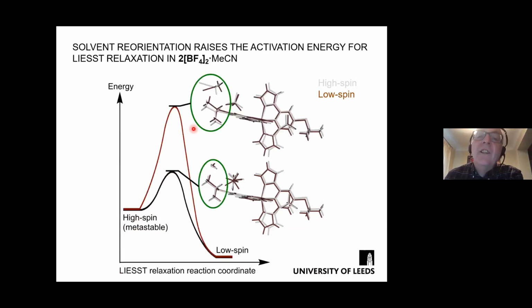And for the acetonitrile crystal, which is the one which has the T LIESST which is too high, the activation barrier is larger because the structure changes in the disordered part of the lattice are much larger than they are for the other compounds in the series. But especially the orientation of the linear acetonitrile molecule, which is rotating by about 30 degrees between these two spin states. And this solvent rotation is leading to a much larger structure change and a much greater activation energy.